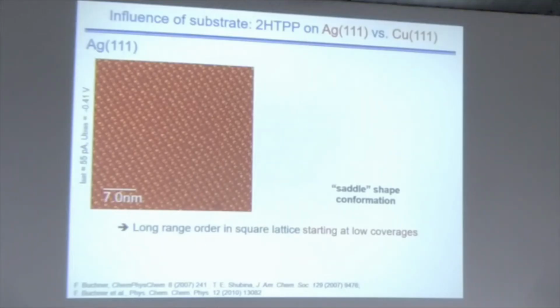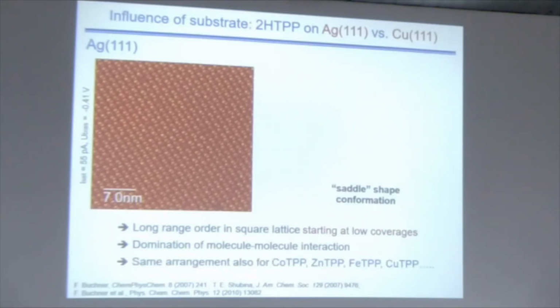Hexagonal surface, quadratic lattice. This is an indication that the order on the surface is dominated by lateral interactions. So the molecule-molecule interactions are the origin of this quadratic lattice, and you find islands starting at low coverage because the molecules want to agglomerate. Also indicative of lateral interactions is the fact that if you put in a metal atom or exchange this metal atom, you always get the same appearance, the same quadratic lattice.